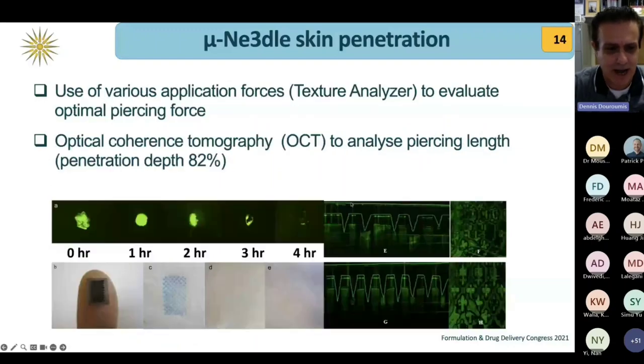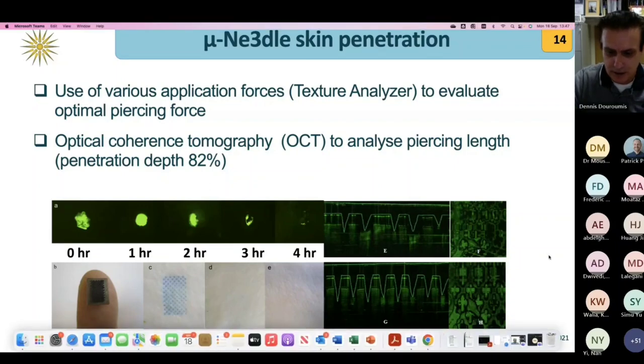Also, we ran some trials to see how long does it take for the skin to absorb the material and also recover, so we don't have any holes on the surface. In about 4 hours, we see that the holes are closing on the skin. This is perfect. We ran also some optical coherence tomography, and we found that depending on the aspect ratio of the needles, the penetration depth can go up to 82%, which is also perfect for our work.